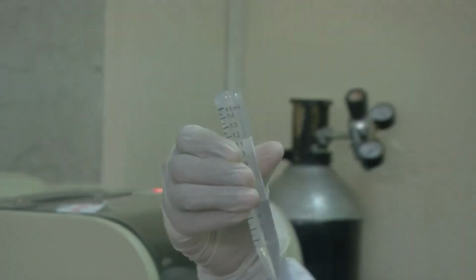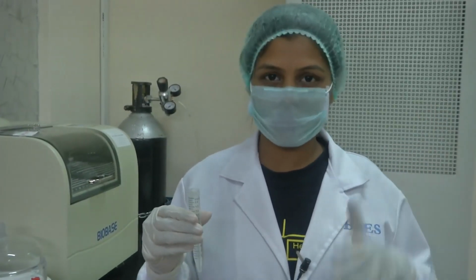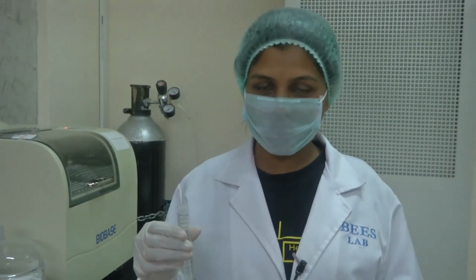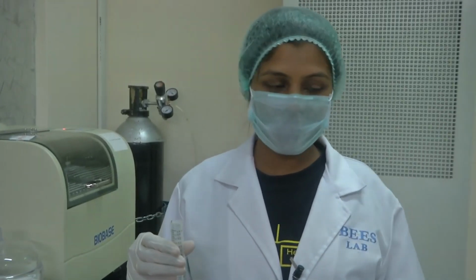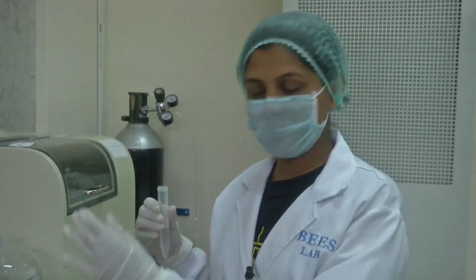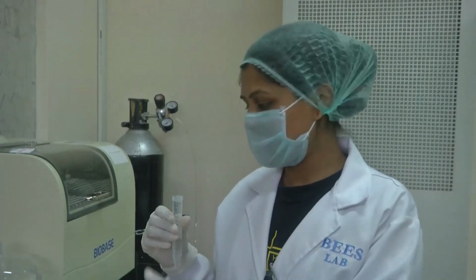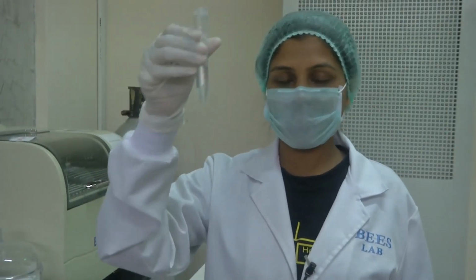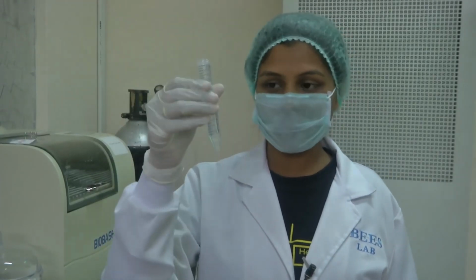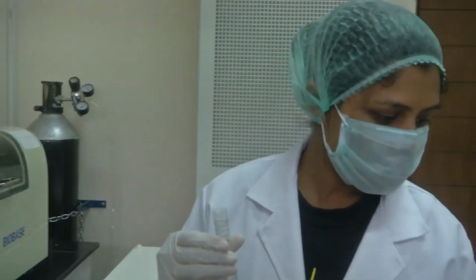Now that we have a clear mixture, let me just repeat the process. We take the elastomer and the curing agent in a 10:1 ratio, mix it thoroughly, and once we have the mixture ready, we put it into the desiccator and degas for 10 to 15 minutes until you see a clear mixture like this. Now, what do we do with this mixture? So, here I have a silicon wafer.